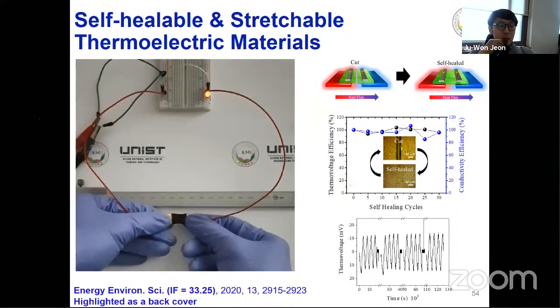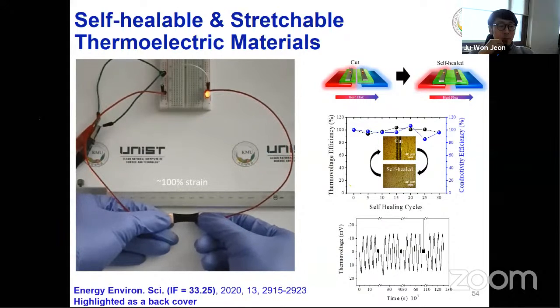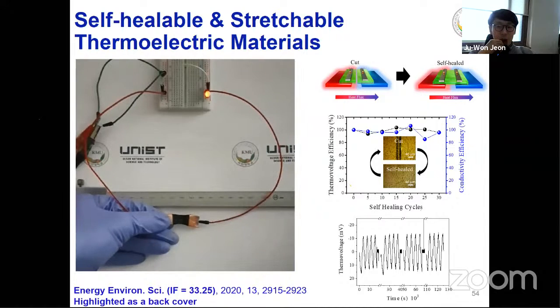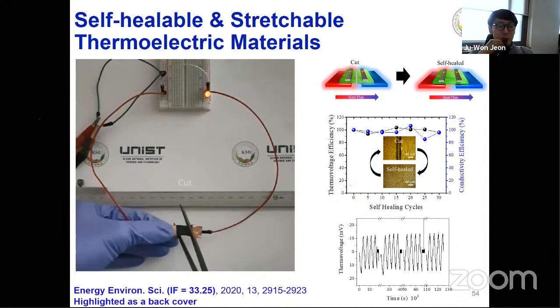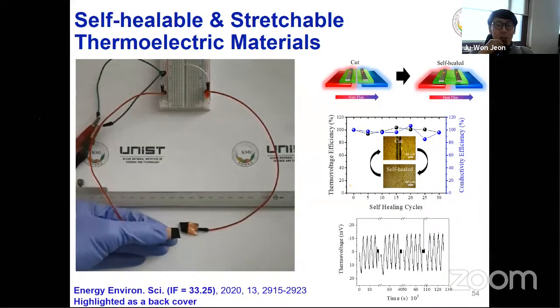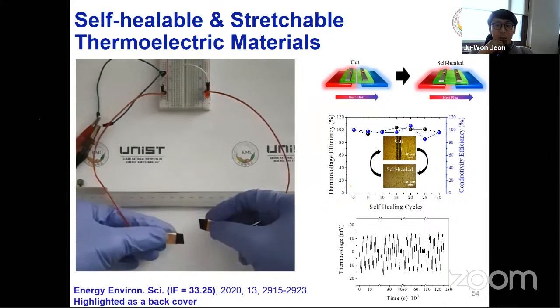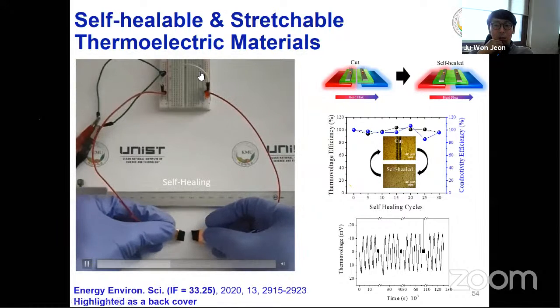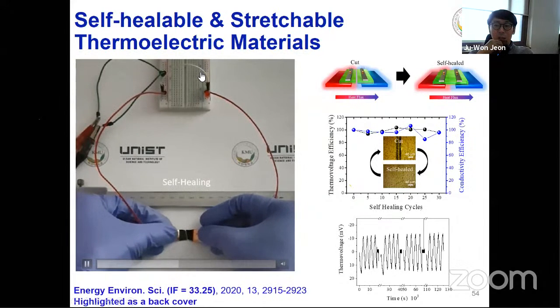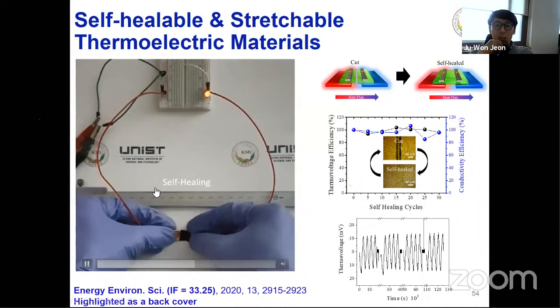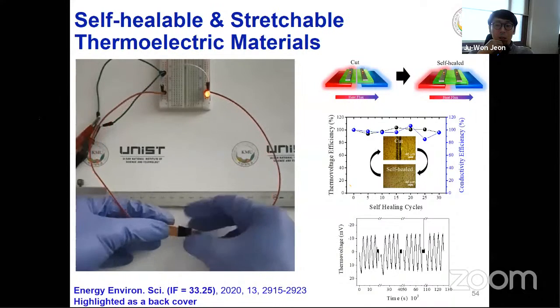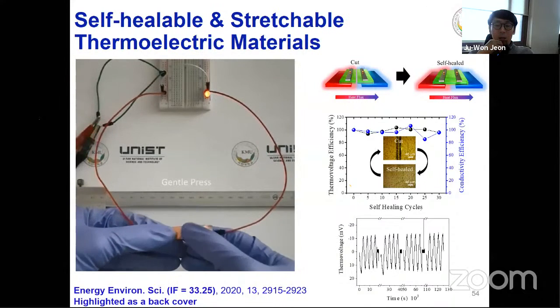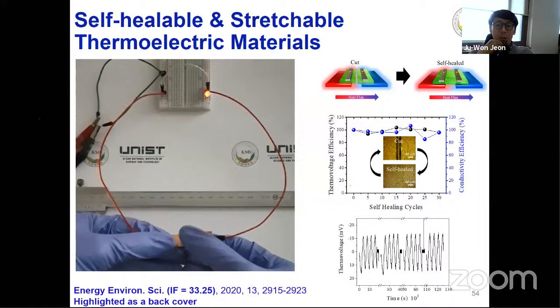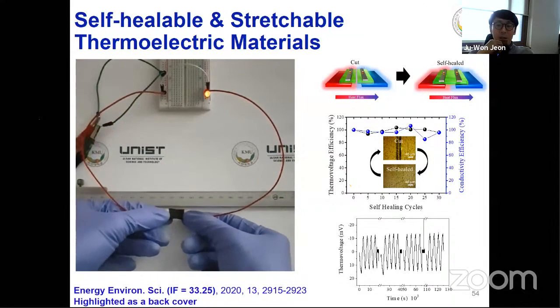So we successfully synthesized this kind of self-healing polymer, which is highly stretchable. It can be stretched up to 750%. And then after cutting it, the light is now off because the electrical connection is off. And just by contacting each other, it starts to self-heal. And then by applying a gentle press, it is self-healing completely.